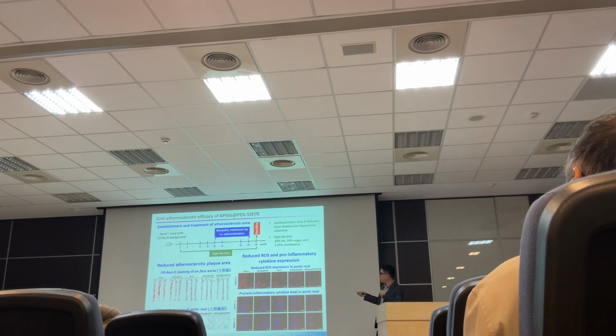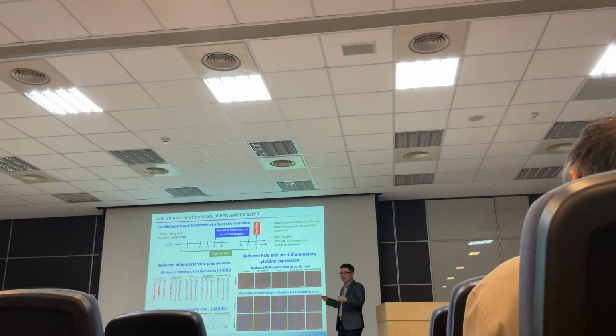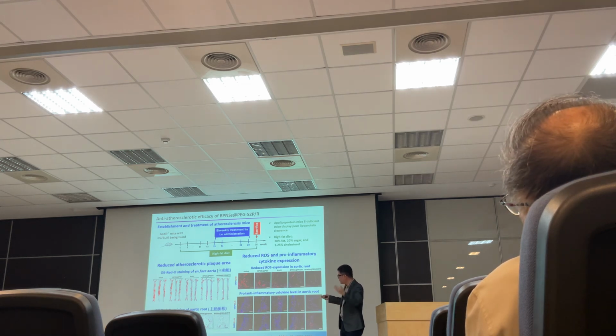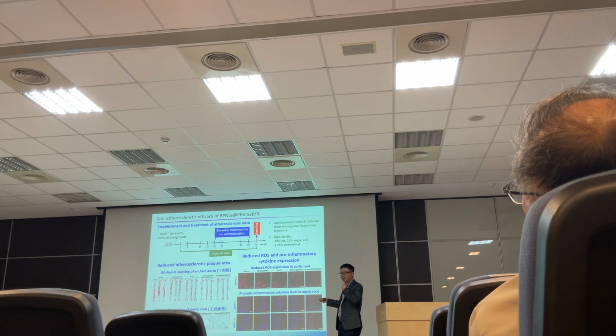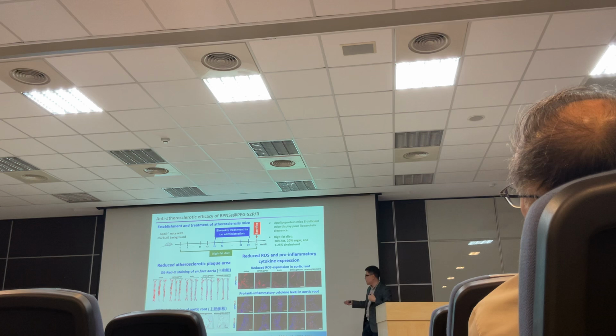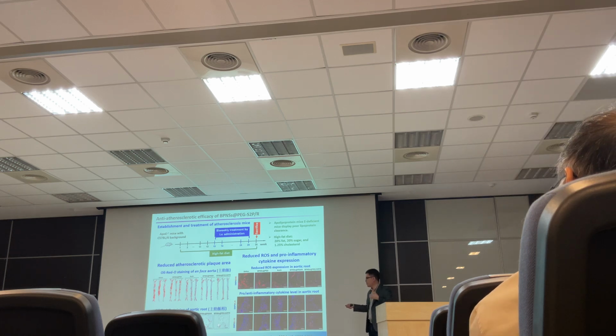And then after 12 weeks of treatment, we isolate and harvest the entire aorta, and then use oil red staining to see the plaque area, the plaque size. As you can see here, the red signal means the plaque. So after our treatment, we can significantly reduce the plaque area compared with the other groups. We also use tissue staining sections to validate that our nanoparticle can really reduce the plaque area in the aortic root.